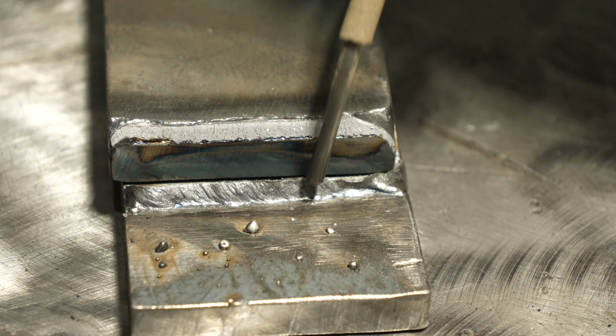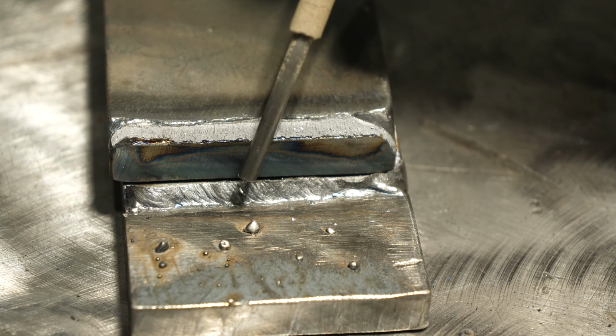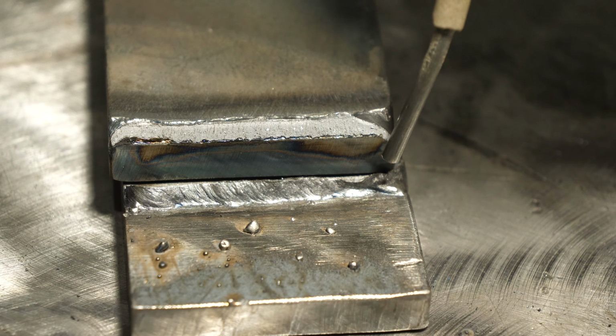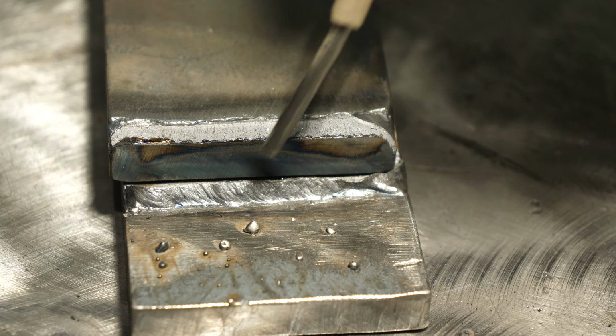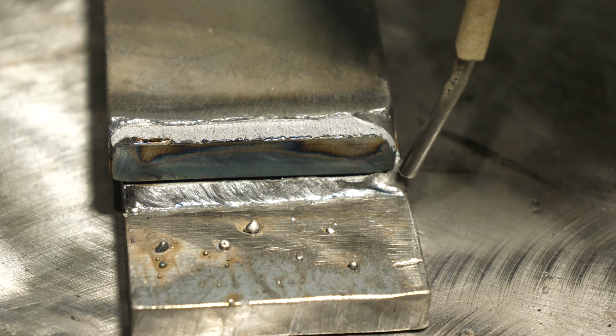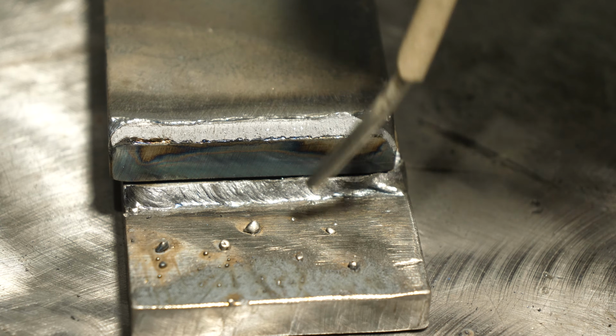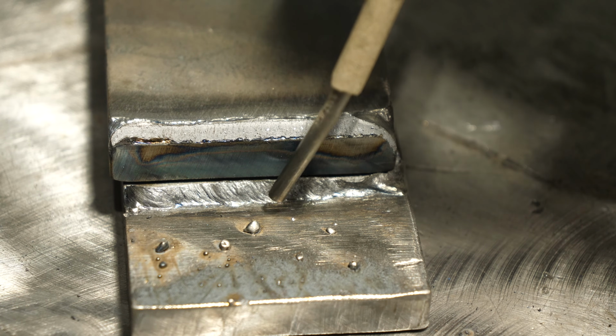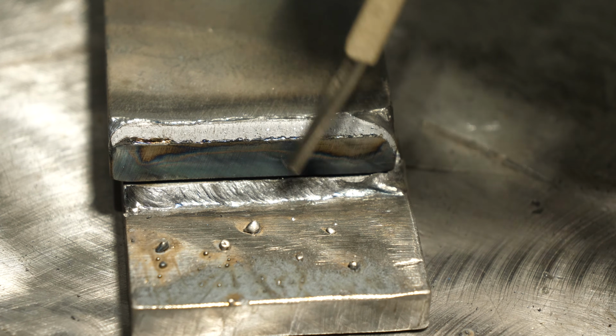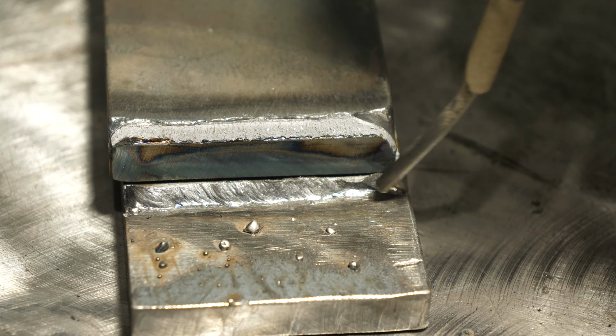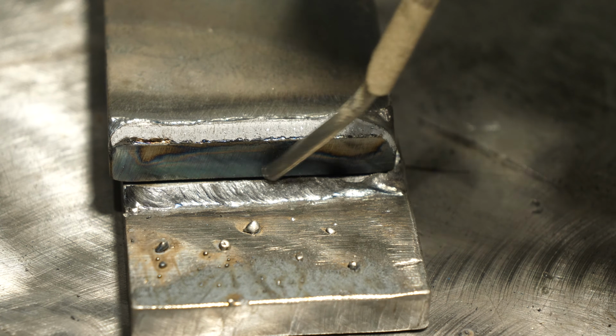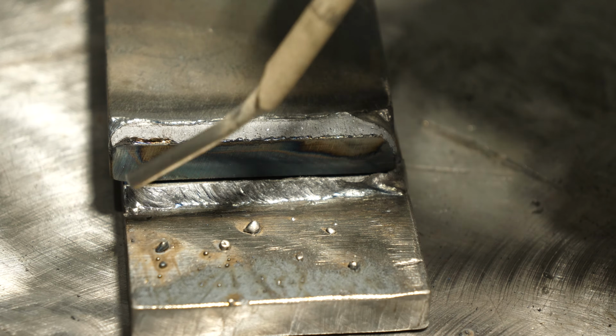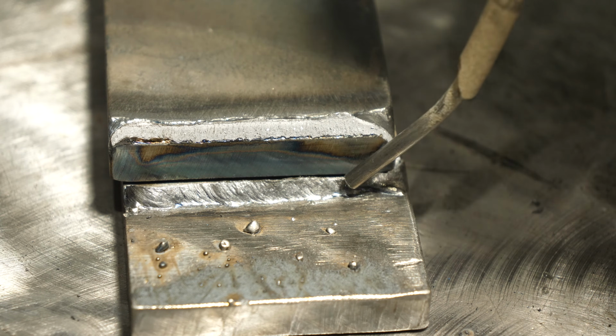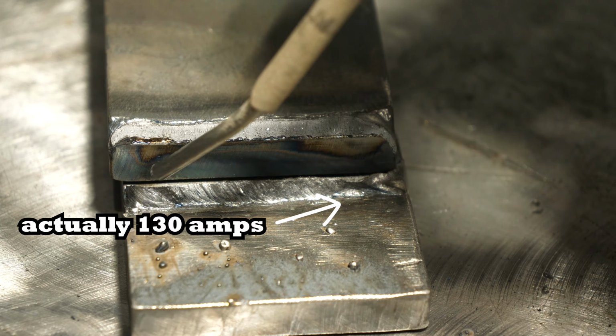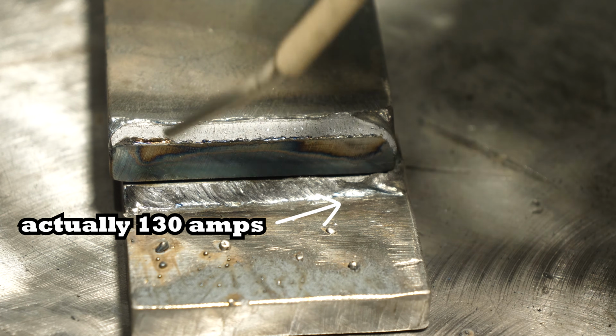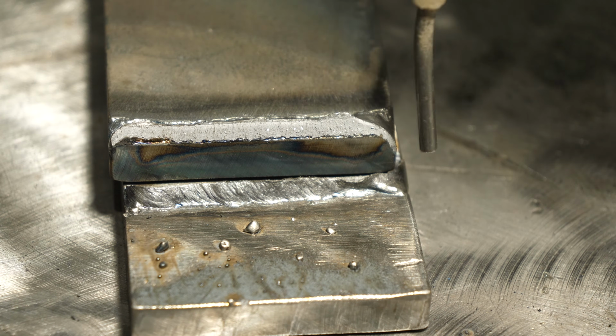I've also tested, and I'll mention it now, running higher amperage, and you know what I found is that, with this particular rod, running more amperage doesn't mean more penetration. Running a bigger rod would likely get you more penetration at the correct amperage, but running like an 1/8 inch rod, it's not going to bite in more with 10 more amps. And I was already running this at 125. I seriously doubt that 140 would have made much difference in this test, and it would have blown the corner out even more.